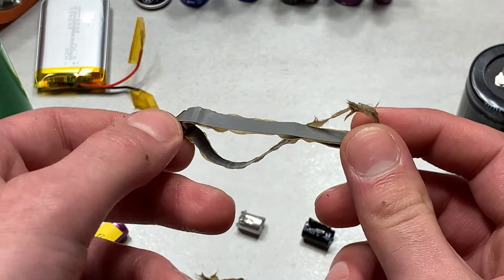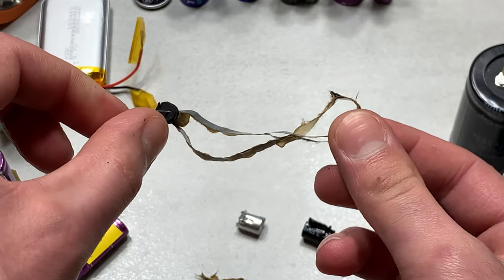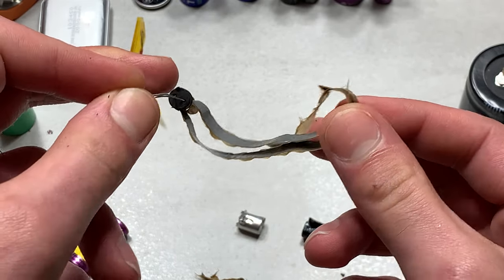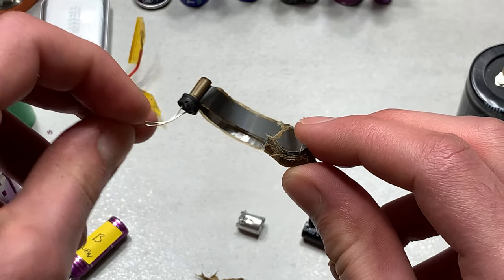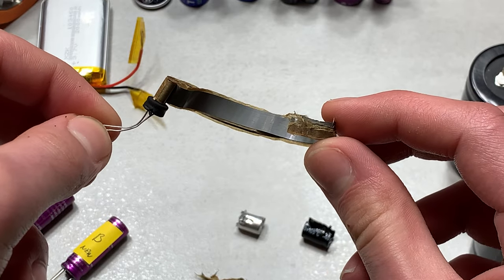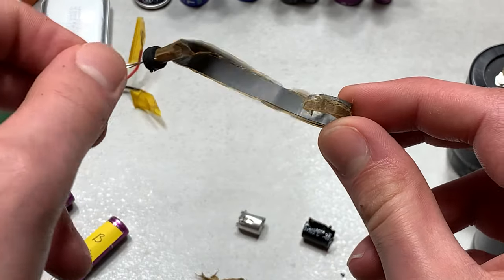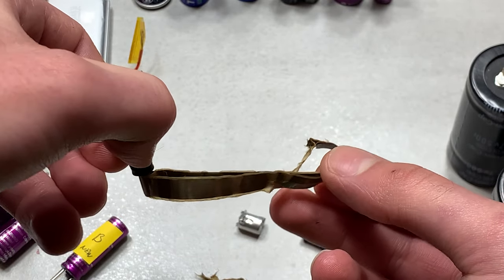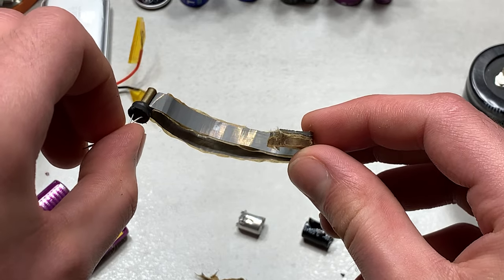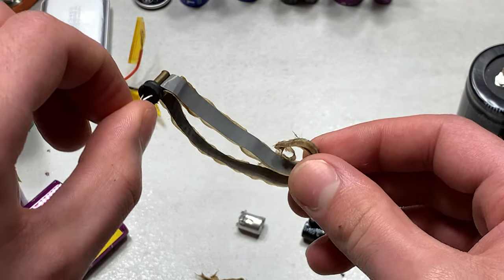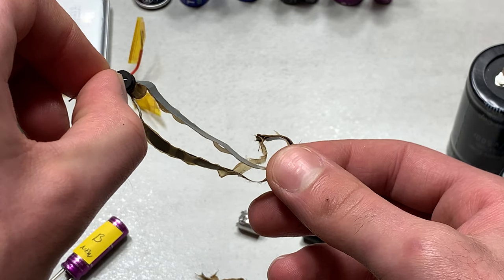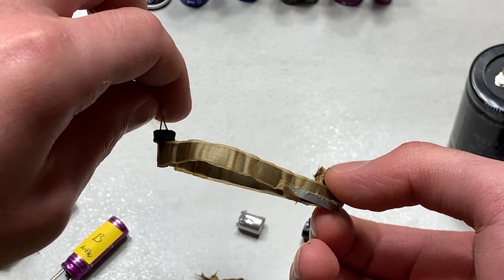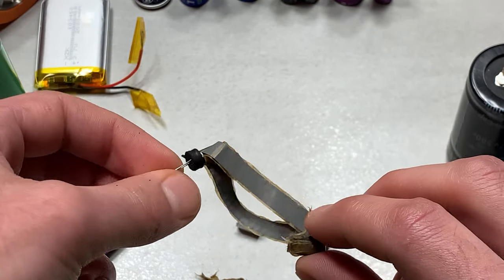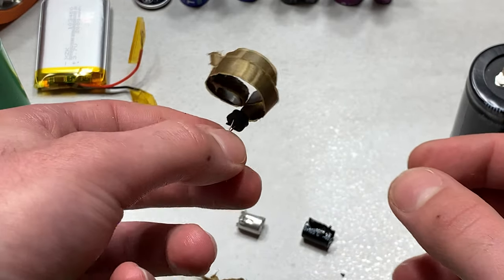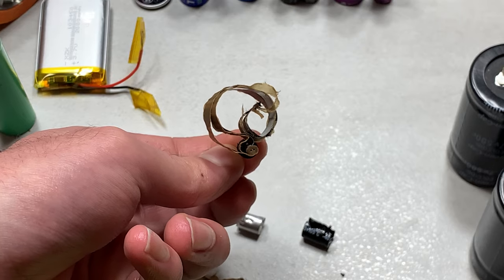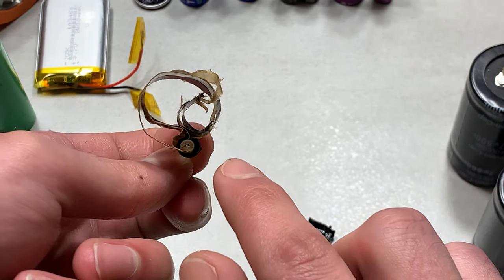So you can see this is just a 470 microfarad electrolytic capacitor. And you can see the alternating layers. We have one and then two aluminum electrodes here, both of which have been anodized to have an aluminum oxide dielectric. That is why you have this dull gray color. And then we have two layers of paper separator soaked in the electrolyte solution and also seems to be impregnated with some kind of gum adhesive. So this should be pretty cool for anyone who has not seen the inside of a supercapacitor, electrolytic capacitor. And you can see there's quite a few more wraps on there.